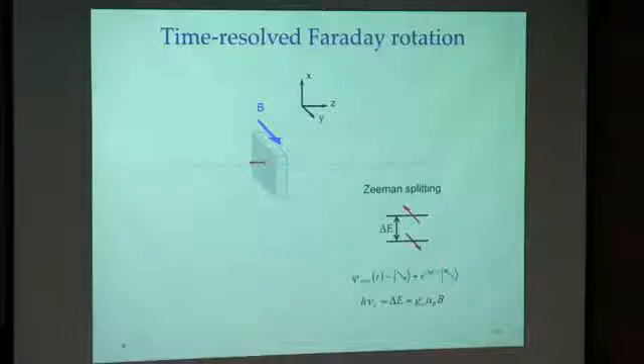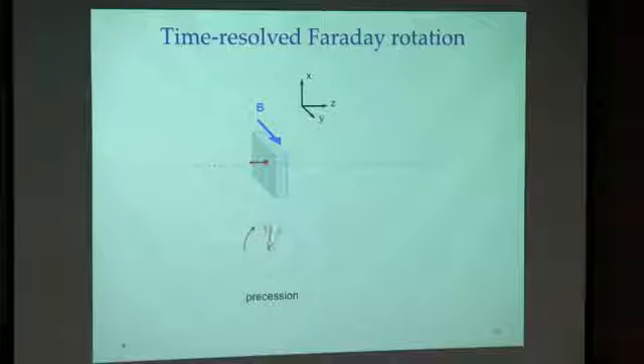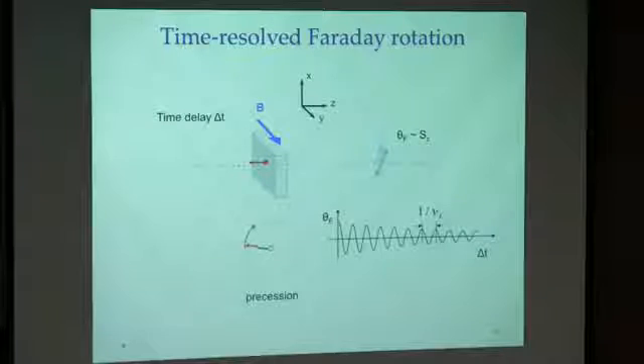And that creates beating between those two states. In a classical picture, it is simply spin precession about the magnetic field. By a linearly polarized pulse, we can measure that precession as a function of time, and we get an oscillatory signal. From that curve, we can get the precession frequency, and from the decay envelope, we get the spin lifetimes. That's the main technique.